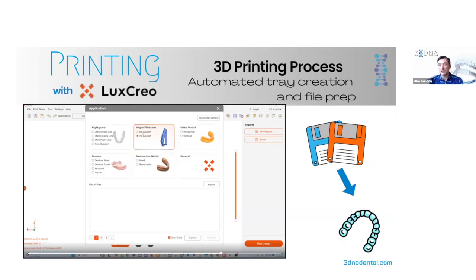It also, with the shape memory, you're redoing that curve each day. With a traditional thermoformed aligner, you begin at let's say 1500 and you go down from there, and within about 3 days it's really not doing anything except holding where you got for bone integration to happen, and then you move on to the next step. Whereas with LuxCreo, and with any direct print aligners, when they warm up, they go back to their shape and they can continue that curve each day. So from a tracking perspective, that's a big advantage. Again, the difference between Graphy and LuxCreo is primarily that flexibility and the way that the resin is treated in the printing and post-processing.